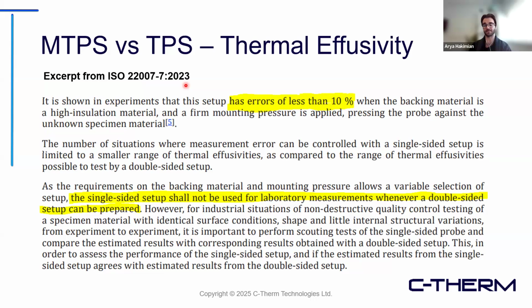Now, the way this is done, the TPS provides you conductivity and diffusivity with some other things. It provides a calculated effusivity here. But a few notes. The error on the measurement is a little bit higher than that of the MTPS for the effusivity measurement. 10% here versus about 5% on MTPS. And there is some work that can be done in TPS in a single-sided operation mode. By default, it's a double-sided method. So you usually place a sample on the top and bottom side. You create a stack. Again, it's a little bit different than the MTPS requirements.